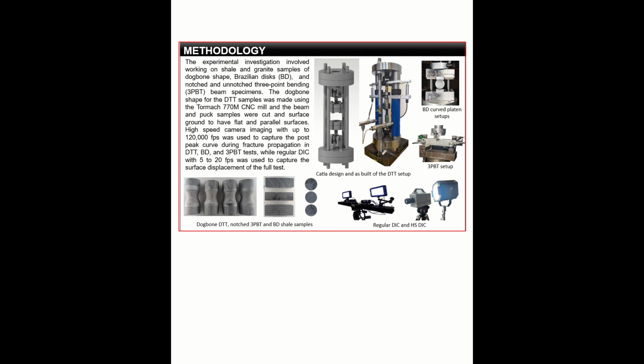This is the in-house built direct tensile testing setup that we have, and the first one is the CATIA design and the final built testing frame. High-speed camera imaging with up to 120,000 frames per second was used to capture the post-peak curve during fracture propagation in the direct tensile test and 3-point bending test, while regular DIC at 5 to 20 frames per second was used to capture the surface displacement of the full test.